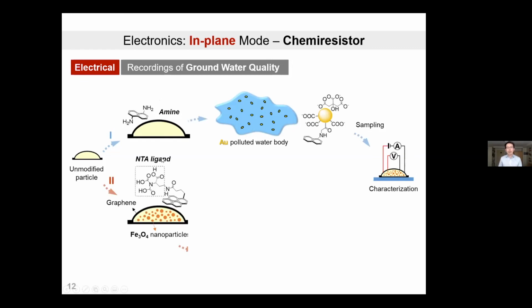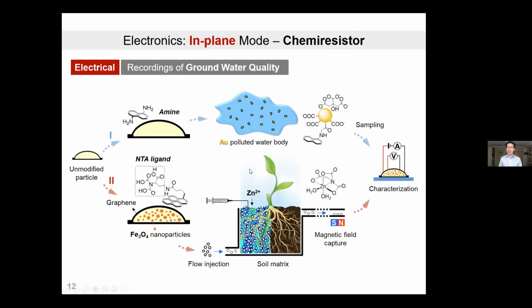On the other hand, if you use something called a nitrilotriacetic acid ligand, or NTA ligand, using the same chemistry, you can functionalize the same particle with a different ligand. Now this suddenly becomes a zinc cation sensor. Here, we put, again, magnetic nanoparticles inside the ink that we print the particle. Hence, the particle becomes magnetic.